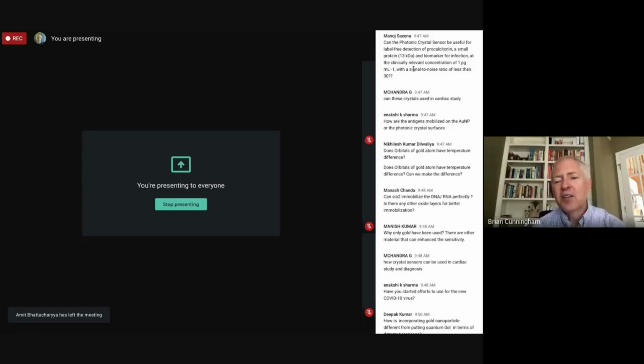So I didn't describe in enough detail, I think, but the photonic crystal requires a high refractive index material to give it its optical confinement waveguiding property. And for that, we use titanium oxide predominantly because it has a high refractive index. However, you could also use other high refractive index materials in place of titanium oxide. So silicon nitride is effective, hafnium oxide can be used.